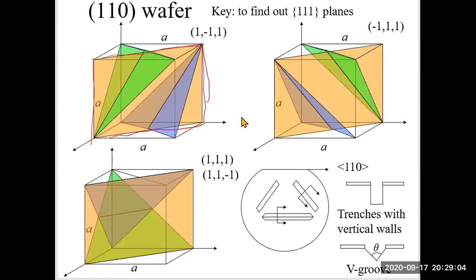Again, we have four 111 planes, so we need to find out their relationship to the 110 plane, which is parallel to the z-axis. The first 111 plane, 1, -1, 1, intersects x and z with equal distance, and intersects the negative y-axis, so -1 here. This plane is actually perpendicular to the 110 plane.